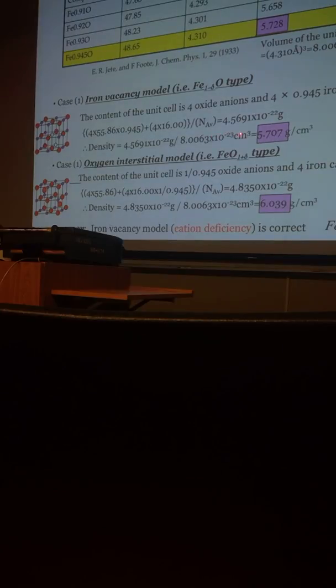In this way, I think what you learned about the MSD 311 Archimedes method is a very useful thing, and it matters how precisely you can measure. Surprisingly, lots of defect people use density measurement so often to actually measure the number of oxygen lost. Those kinds of things can be directly measured, and there is no assumption involved.